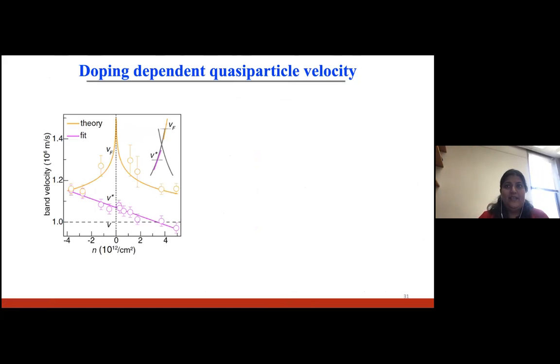So next, I'm going to show you how the interaction strength in our device affects the doping-dependent shape of the Dirac cone. We can do so by extracting the Fermi velocity at the Fermi level, and then extracting the band velocity below this Dirac crossing. I think we did it around 300 meV below the Dirac crossing in the valence bands. I am showing the Fermi velocity here. These are the orange data points that you see here.